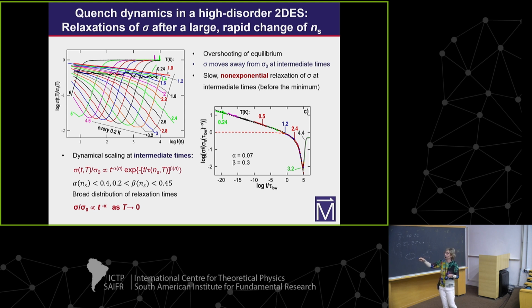So each of these is a kind of relaxation, non-exponential relaxation that is characteristic of glasses, and it reflects the presence of a broad distribution of relaxation times in the system. This is really the same kind of relaxation that has been observed, for example, in spin glasses above the glass transition temperature as you approach that.